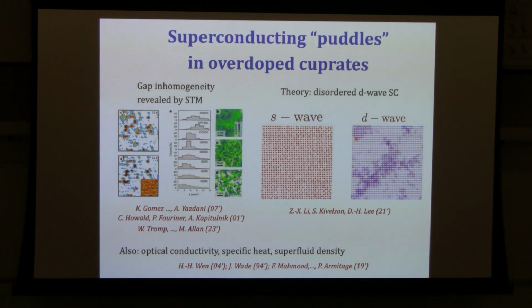But because of the random distribution of impurities, it won't be destroyed at the same temperature or field at the same time. Okay, so this is a picture from a simulation, basically of a BCS mean field theory of a disordered S-wave versus D-wave superconductor. And this is just a picture of the local superconducting order parameter. And you see that it develops kind of spontaneously these structures in the D-wave case.